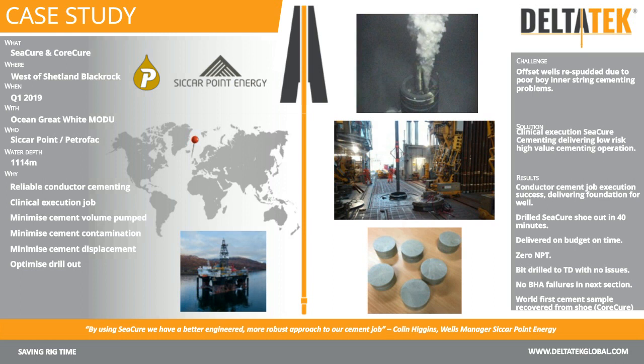The deployment was a great success, the first recovery of core cure cement samples from underneath the DeltaTek SeaCure ball in the latching adapter. What you can see with the pictures on the right of the case study are some of the captures from the offshore deployment. In the top, following the rupture of the rupture disc and the successful internal circulation to clean the inside of the casing, you can see there the ROV's footage of capturing the fluid effluent out of the ball valve. In the middle picture, you can see the SeaCure BHA entering the low-pressure wellhead housing suspended on the clamp in the rotary table, and at the bottom you can see the core cure cement samples recovered at the end of the successful job.